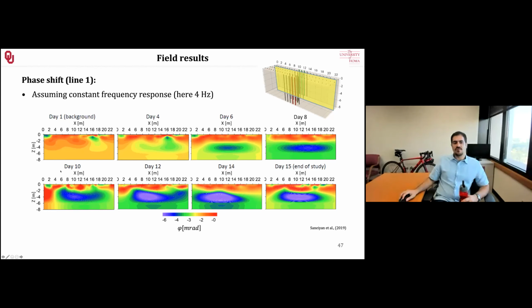Clearly, as you can see, over time, the line that was closer to the injection port is showing evidence of signal increase, matching the treatment area that we had. So the phase has actually increased over time, all the way to around 6 milliradians. And bear in mind, we use phase as a negative value because it takes time to measure it. It's like a negative value compared to the actual time. It's a delay, so it's negative.